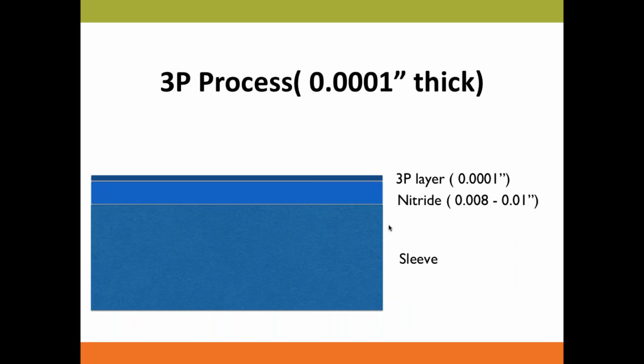The advantage or the difference of this 3P process compared to the conventional coating process, which is physical vapor deposition, is that PVD will suffer line of sight limitation. That means it's very easy to coat the OD, outer diameter, but it's very problematic to coat the ID, inner diameter. But for the sleeves, the ID, inner diameter, is the most important part that we want to protect from molten aluminum. For the 3P process, there's no problem to form the 3P layer on the OD or ID.